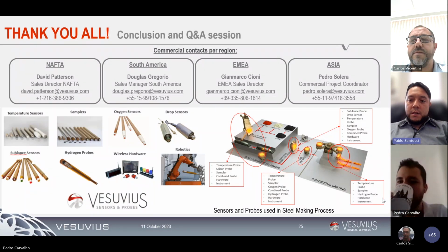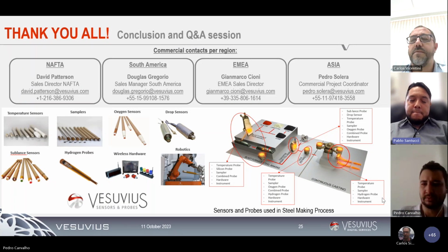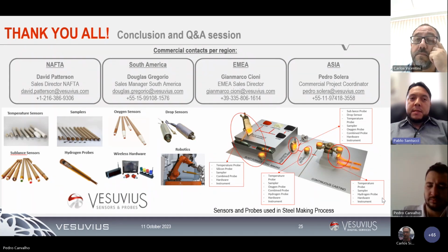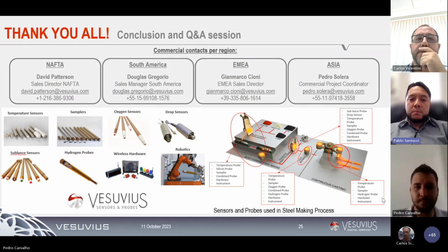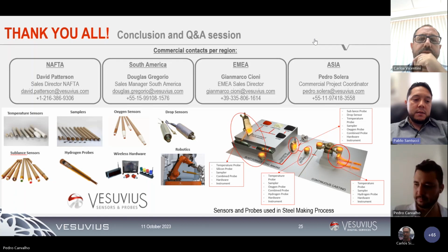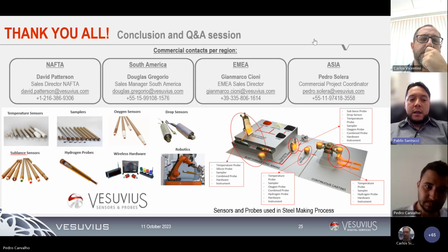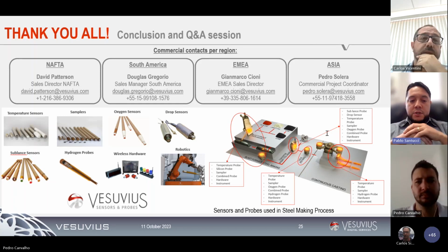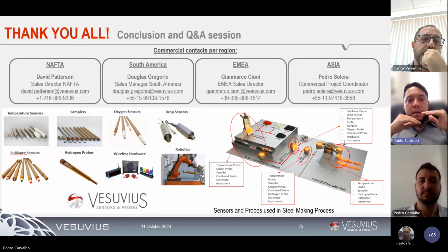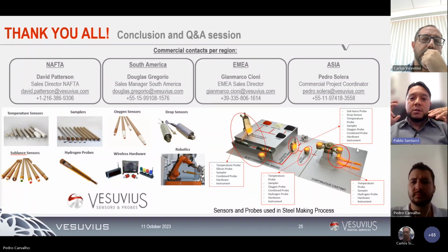In terms of quality defects that can appear in the steel casting, probably the immediate containment action would be to slow the speed of the continuous casting machine once high levels of hydrogen are reached. For example, if a certain steel mill tends to control the continuous casting machine hydrogen up to 6 ppm, and they suddenly get 7 or 8 ppm in the next heat, they will probably slow down the speed of the continuous cast so that they can avoid this breakout.